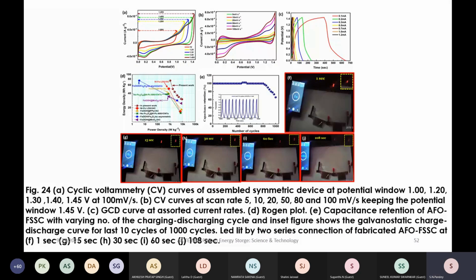The same thing we have done here, that is cyclic voltammetry of the assembled symmetric device at potential windows of 1.00, 1.20, 1.30, 1.40, and 1.45 volt at 100 millivolt per second. So for that we have done this CV, and then the B part, the CV curve, once we have optimized it, one can have this CV curve at different scan rates. Further, one can go to the galvanostatic charge discharge curve. The same type of thing we have to do, and for the different current rates we have the charge discharge, with the highest value at 0.1 milliampere.